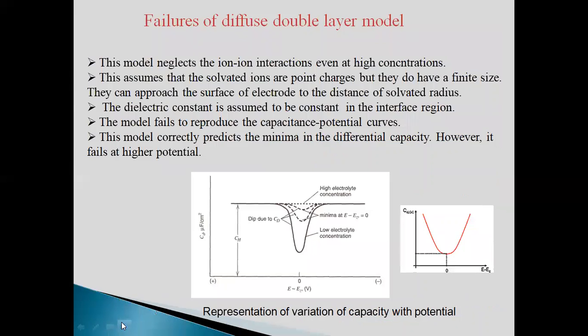So, what are the failures of this diffuse double layer model? One of the most important failures is that it assumes that the ions are point charges, so they can approach the surface of the electrode without any restriction of distance. But this is not so. They are also solvated. So this was one of the most important failures of this model. Another failure is that the dielectric constant is assumed to be constant in the interface region, while it is not so. The model also fails to reproduce the capacitance potential curves that are known as electrocapillary curves.